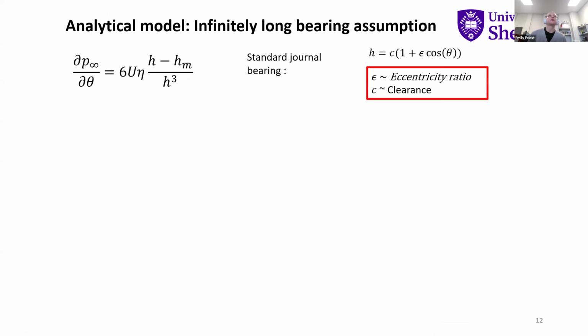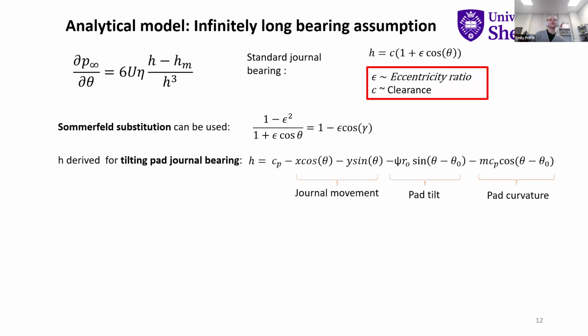So we went ahead and found the infinitely long bearing assumption, and we're using a Sommerfeld substitution, which is used for a standard case, as you can see here, where the film thickness is just there. But the issue we have with using the substitution with the film thickness for a tilting pad journal bearing is that we have to consider all these different factors involved in the film thickness: journal movement, pad tilt, and pad curvature.